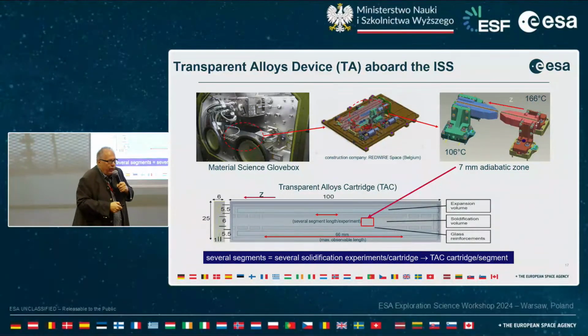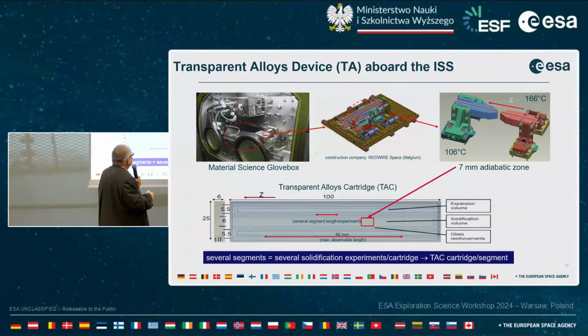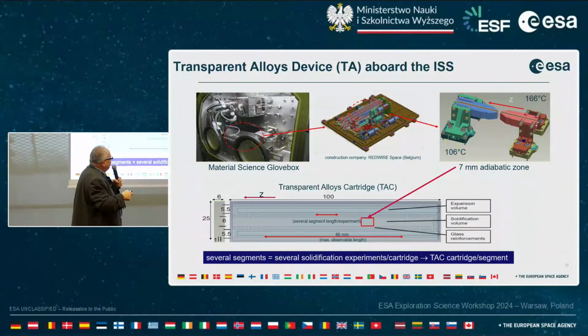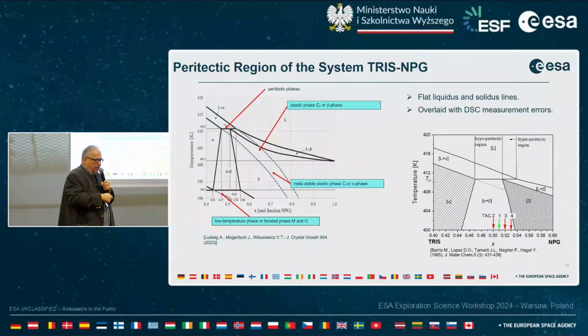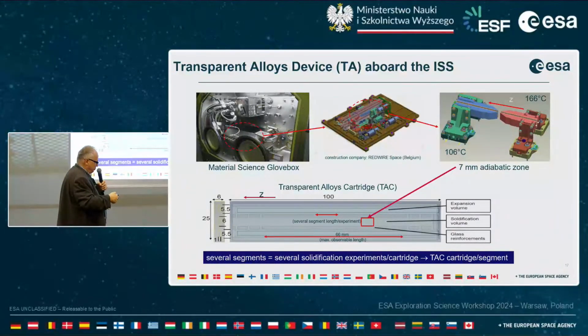My colleague from France gave a short overview of the transparent furnace device and the microgravity setup, so I keep it very short. It's a Bridgman furnace, like the one used at DLR, but we use an organic material. So we have 4 clamps, 2 hot, 2 cold, and we have an approximately 10 centimeter long glass cartridge. Since we have very long experiments and don't need the whole length, we divide this length into several sections, because with microgravity there is no convection in the liquid, and therefore we always have more or less a fresh concentration which we can perform.